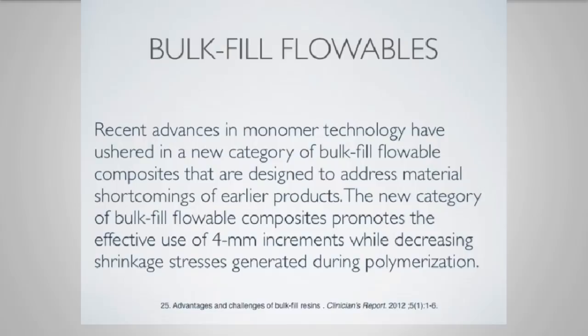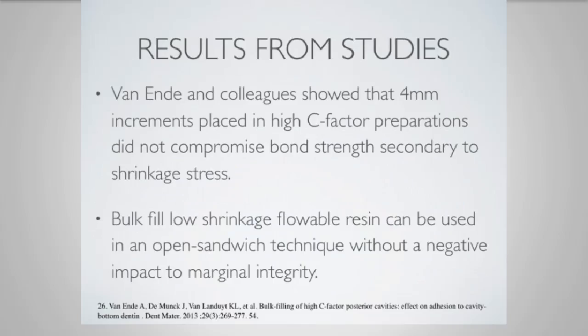And so what are the results from the studies? People obviously are doing studies to see, is this true? Can this be true? In pulling the results from the literature, we're seeing that 4 millimeter increments placed in high C-factor preparations did not compromise bond strength secondary to shrinkage stress. That's awesome. Bulk fill low shrinkage flowable resin can be used in an open sandwich technique without a negative impact to marginal integrity.